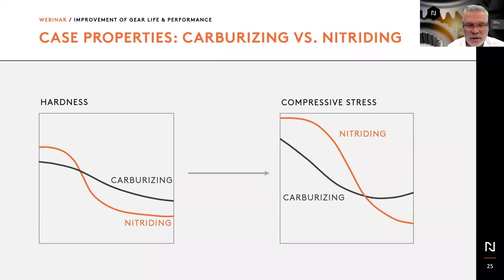Again, same illustration, but much simpler. On the left-hand side, you see hardness for nitriding in orange, and the initial hardness is higher. Carburizing initial hardness is lower, and carburizing usually produces a harder core. Nitriding goes down to the core hardness of the original heat treatment on the steel component. But you can also see compressive stress, which is extremely high for nitriding and much lower for carburizing. And this compressive stress is what accounts for the difference in endurance to bending.